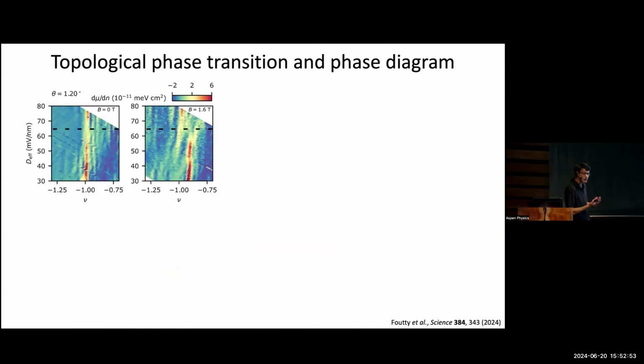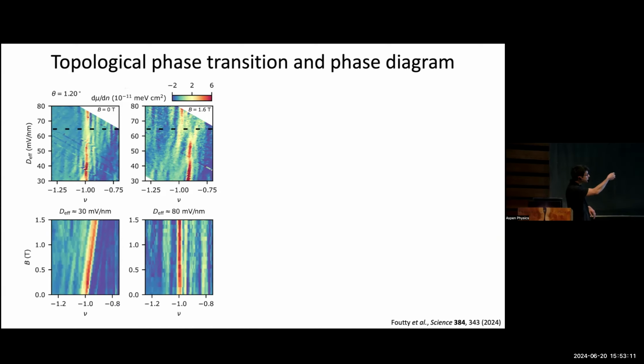So we can also look in a non-zero magnetic field, where a trivial state with Chern 0 is just vertical, the topological state is diagonal, so the density at which it occurs will be different for what should be the trivial state at high displacement field, the topological state at low displacement field. Indeed, if we just take cuts, at high displacement field and at low displacement field, we see yes, diagonal at low displacement field, state is vertical at high displacement field.